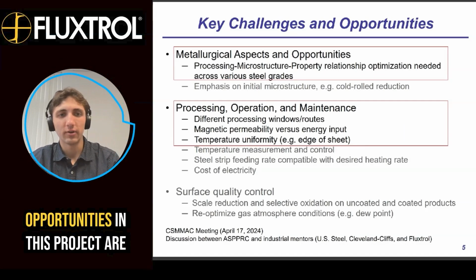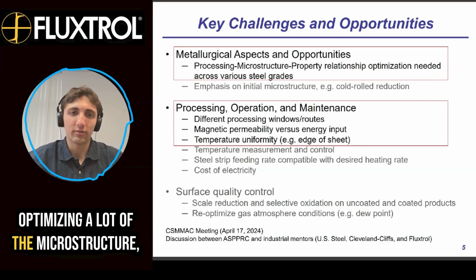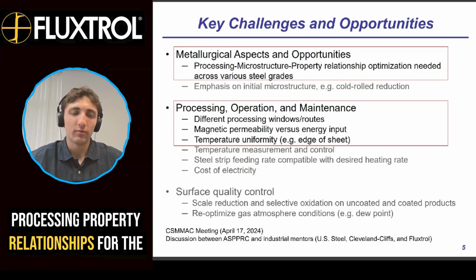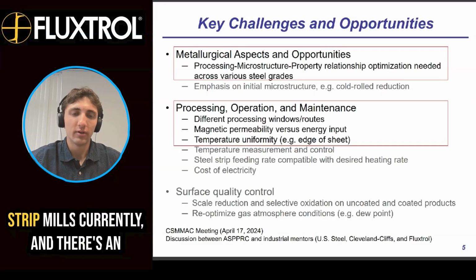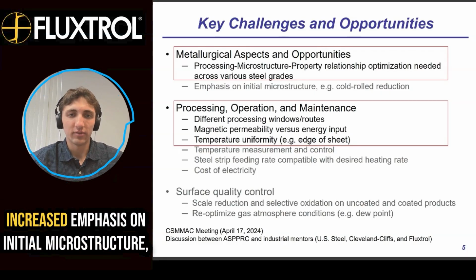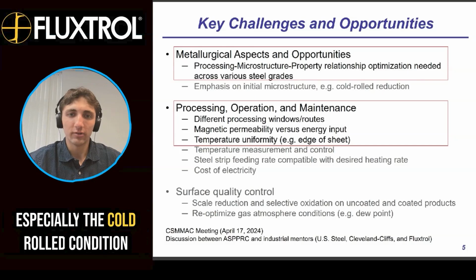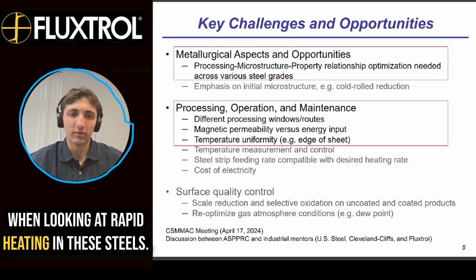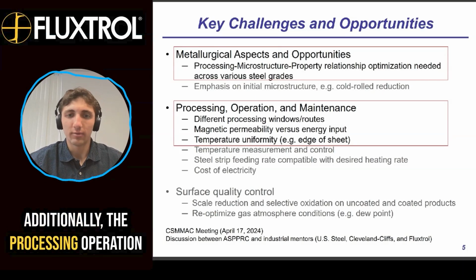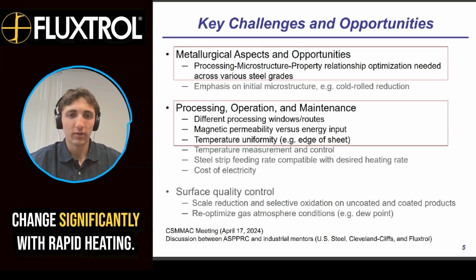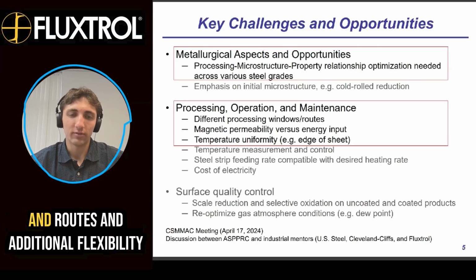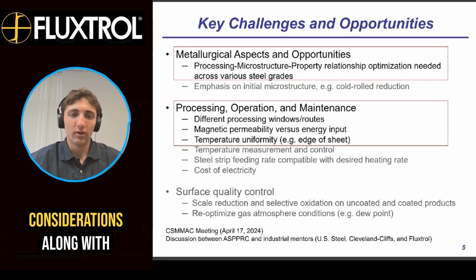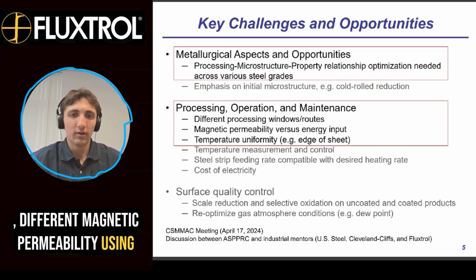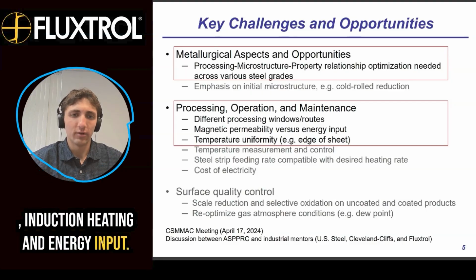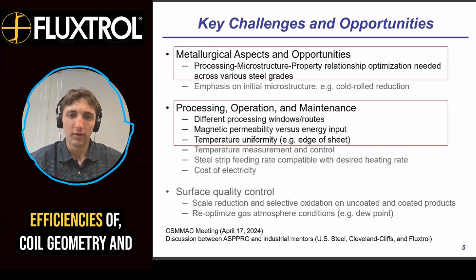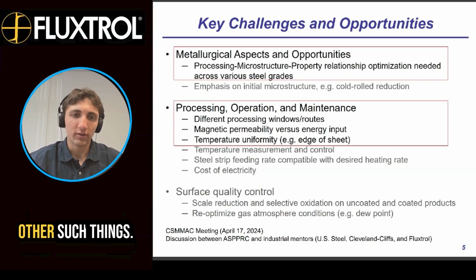Some of the key challenges and opportunities in this project are optimizing a lot of the microstructure processing property relationships for the various steel grades being produced on strip mills currently. And there's an increased emphasis on initial microstructure, especially the cold roll condition, when looking at rapid heating in these steels. Additionally, the processing operation maintenance parameters will need to change significantly with rapid heating, and there's different processing windows and routes and additional flexibility considerations, along with different magnetic permeability using induction heating and energy input. So you have to consider the different efficiencies of coil geometry and other such things.